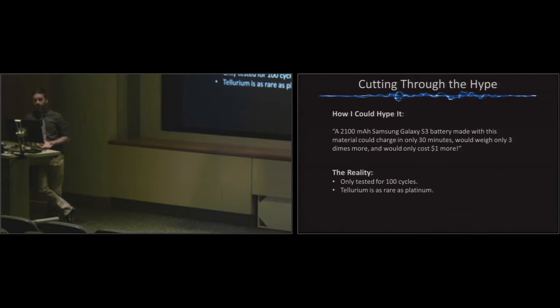In reality, I only tested it for about 100 cycles. That's due to the limitations of being a grad student. I don't want to be here forever, so I have to kind of cut it off at some point. But really, you need to go about 1,000 cycles without losing more than 20% of your capacity in order for it to be something that you could use in industry.